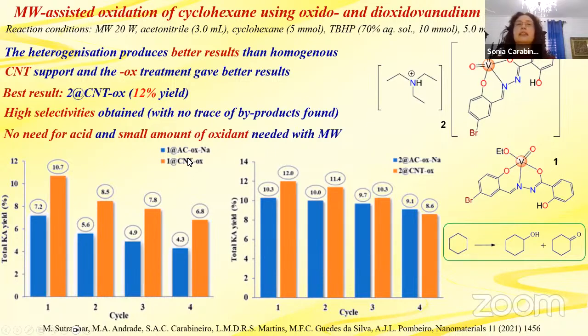So we see here that carbon nanotubes are better than activated carbon, but the activity decreases with time. So complex 2 was better. And again, the activity loss was due to leaching.